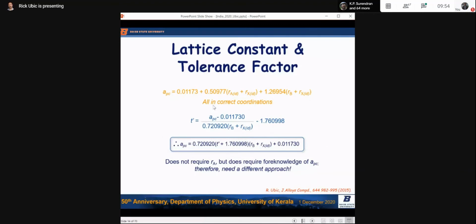So in order to tackle that problem, we go back one little step away from our everything's-in-6-fold-coordination model, one step back to everything's in the right coordination, right? So it's not the best fit we had, but everything is in the right coordination. Because when we start playing around with things, we want things to be in the right coordinations. So this was the equation that described those orange data points, where we did the regression in 2 variables, but everything was in the right coordinations, right? It gave us a good fit, 0.7, I think, slides back.